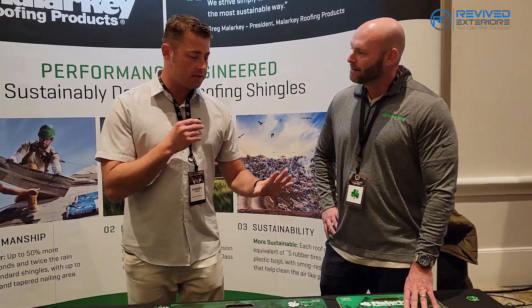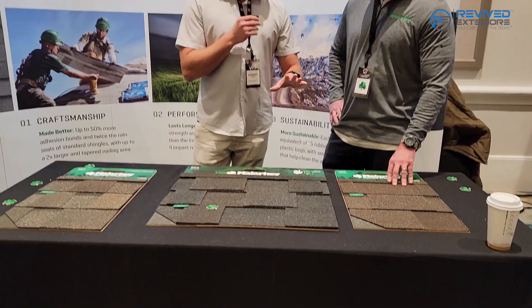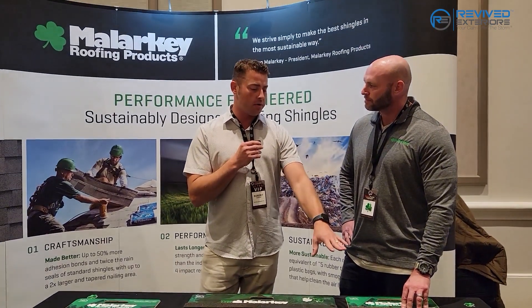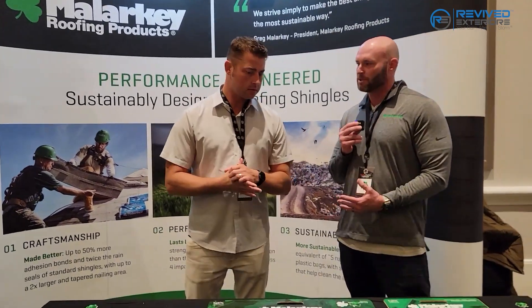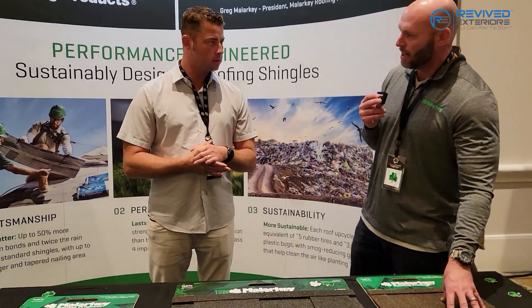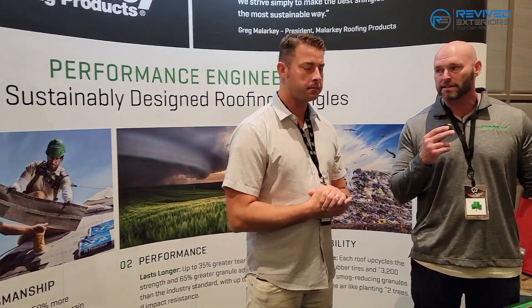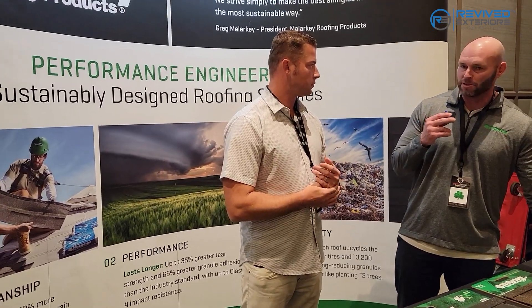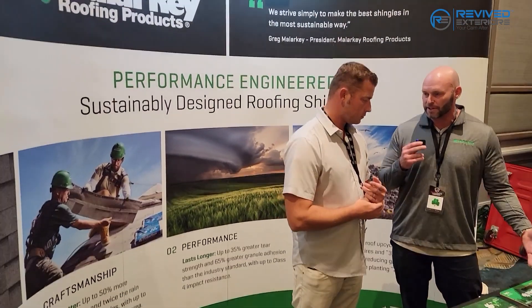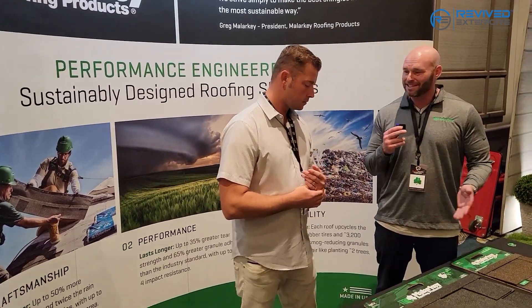What would you say is the key difference between polymer-based shingles and an asphalt shingle? To put it in easy terms, this is a younger piece of asphalt than you would get from what we call an oxidized asphalt shingle. Oxidation is the process manufacturers use to raise the softening point of asphalt to make it usable as roofing. The softening point of asphalt is about 120 degrees. Your average roof temperature in Chicago, if it's vented correctly, is between 160 and 170 degrees.